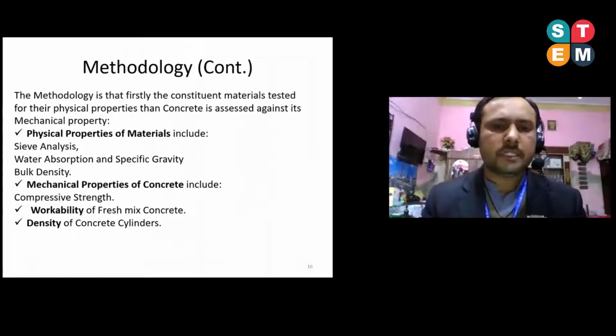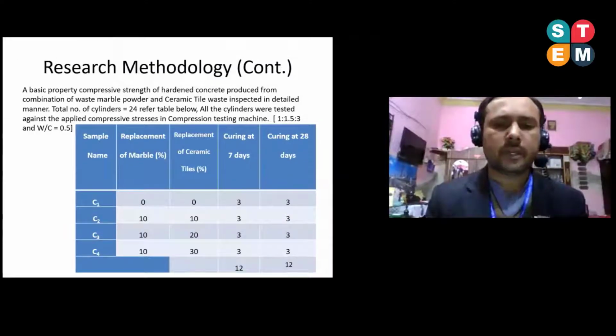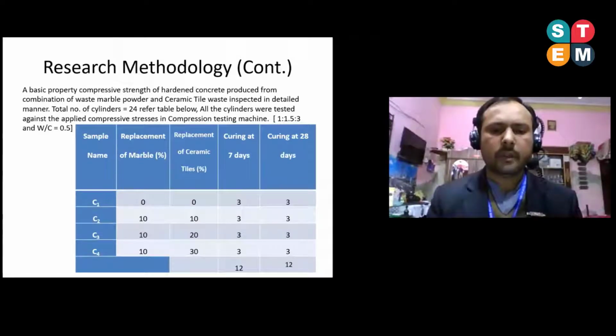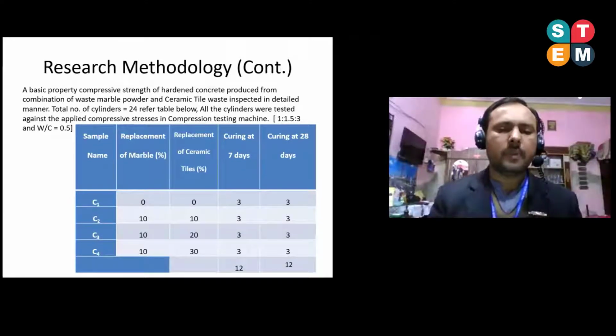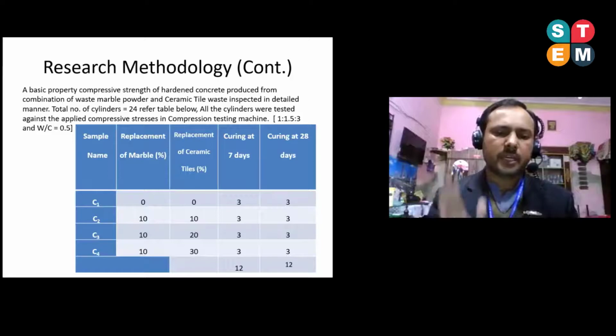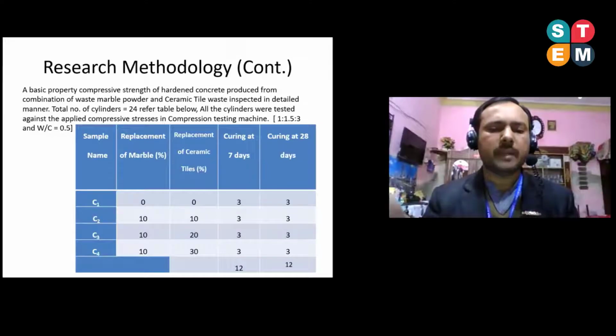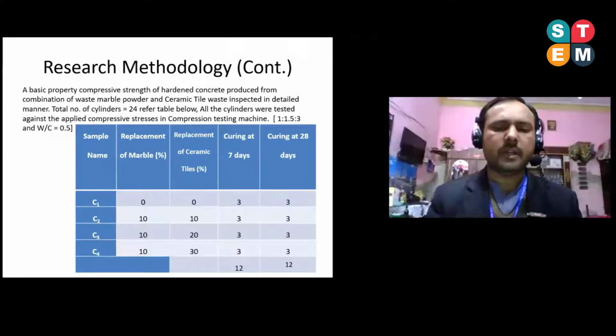These are the methodology details, and in this study, we total prepared around. Here you can see there are some coding: C1, C2, C3, and C4. So C1 represents the control mix, means without any waste material, which can compare with the recyclable materials. C2 represents the 10% marble powder. In this study, we fixed the marble powder as a 10% replacement. Then we vary the ceramic tile waste by 10%, 20%, and 30%. And the three samples were prepared. In total, 12 samples at 7 days and 12 samples at 28 days were tested.